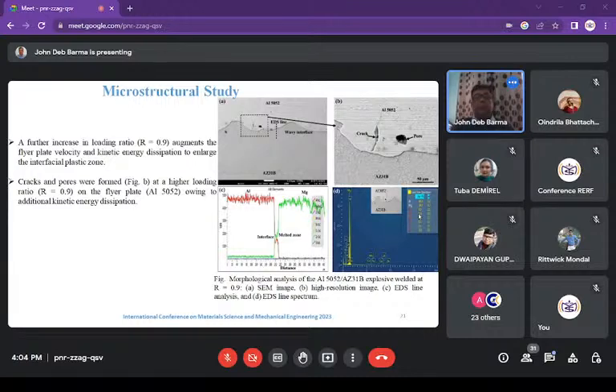which augments the flyer plate velocity as well as the dissipation of the kinetic energy, it enlarged the interfacial plastic zone. So what happened? It resulted in the formation of the interfacial waves. As you can see, it is wavy with a higher wavelength, and the wavelength is found to be 840 micrometer and amplitude to be 166 micrometer.